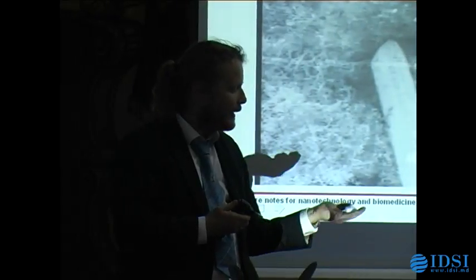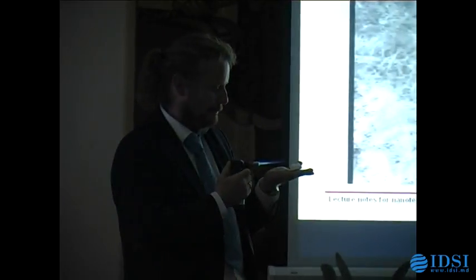And you see it's glowing, it's getting yellow. This has to do with surface oxygen vacancies. Now it's yellow, I don't know if you can see it, now it's white again. So some oxygen is going away from the zinc oxide, oxygen vacancies, and now it's back again. Now I can make it hot again. And now I can immediately touch it.